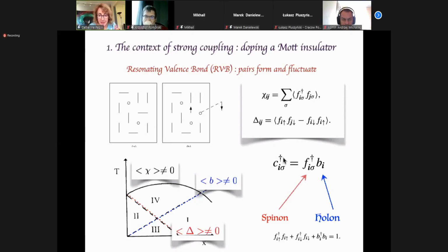So how do you describe the pseudogap in this phase diagram? Well, the spinons are pairing, like a d-wave pairing of Cooper pairs, but it's on these spins below this red line over there. And here you have this particular hole of spinons, which is this black line here. And the holons are condensing below the blue line over there. When one of the two species condenses, this is reconfining. So below the blue line and the red line, you have confinement. And since you have pairing, you will get the Cooper pair, so it will make a superconductor. On top of it, here, you would get this preformed pairing of spinons, which is this valence bond spin liquid. Namely, this pseudogap is a spin liquid for Anderson.